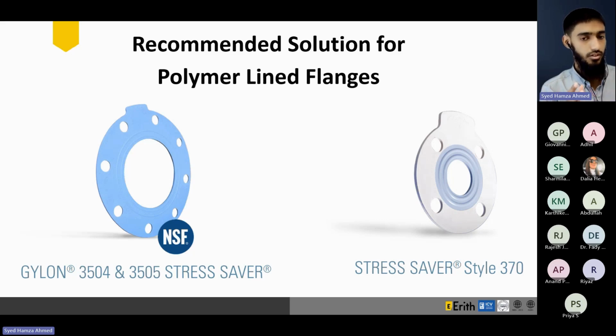In many cases, a stress saver type gasket is the best option for these connections, as these gaskets are designed to seal at the extremely low available assembly stresses that are generated in FRP flanges. It is important to confirm that the torques do not exceed the maximum stress recommendations while using rubber stress saver gaskets. We do have fluoroelastomer as well as EPDM bonded with PTFE stress saver gaskets, as well as pure PTFE stress saver gaskets.